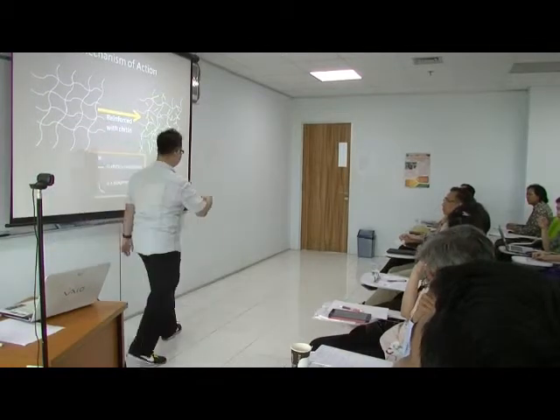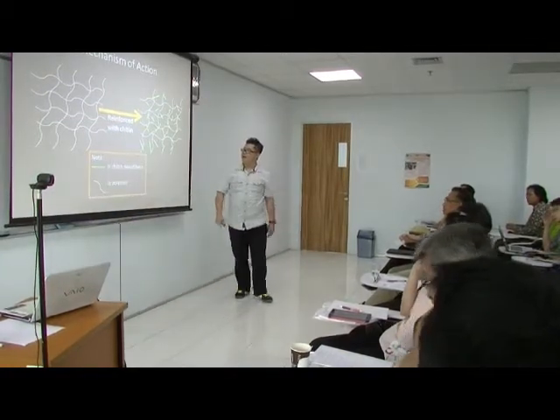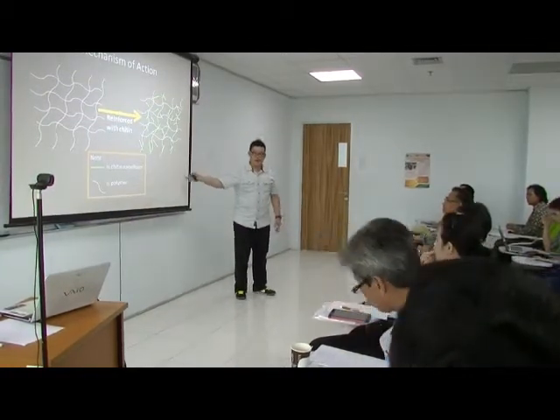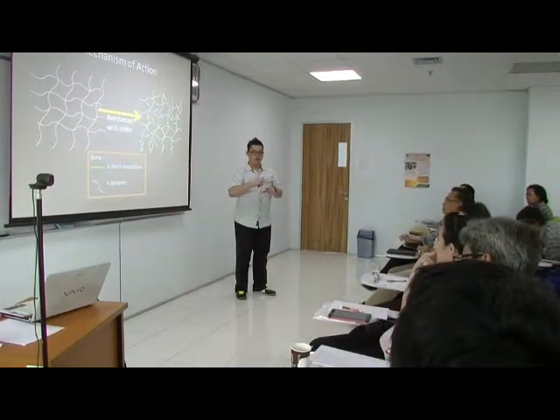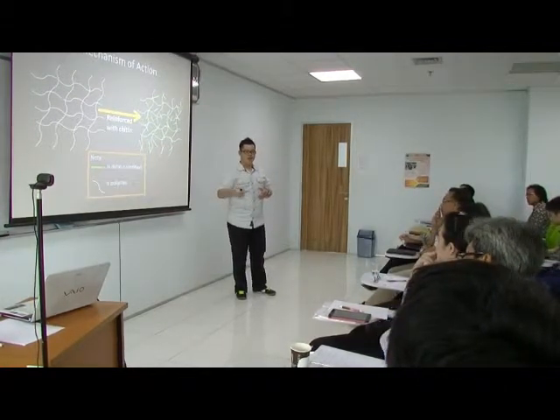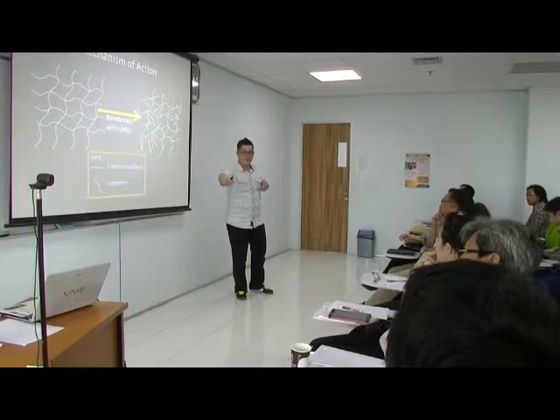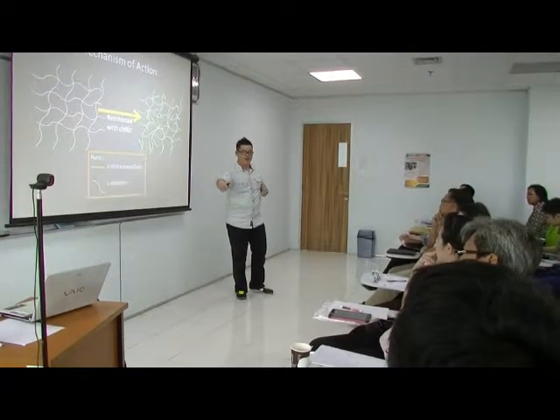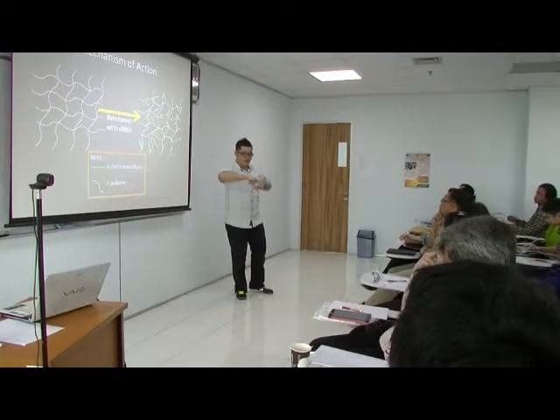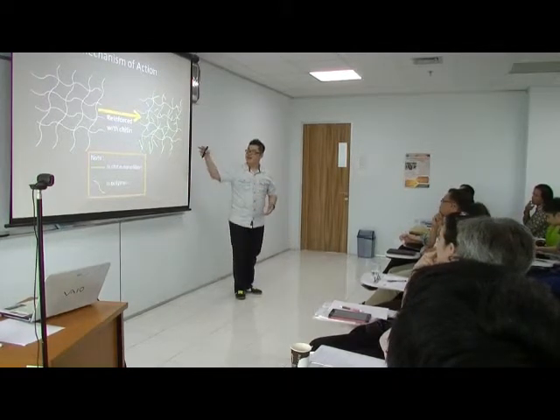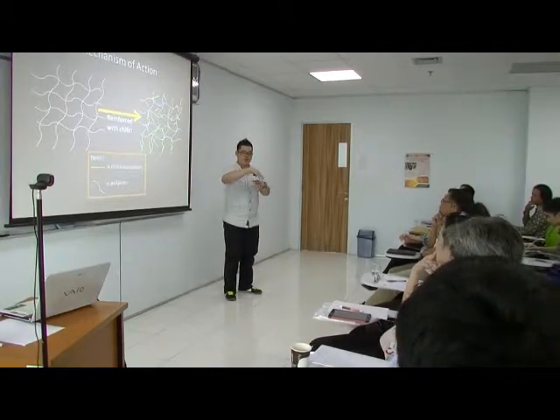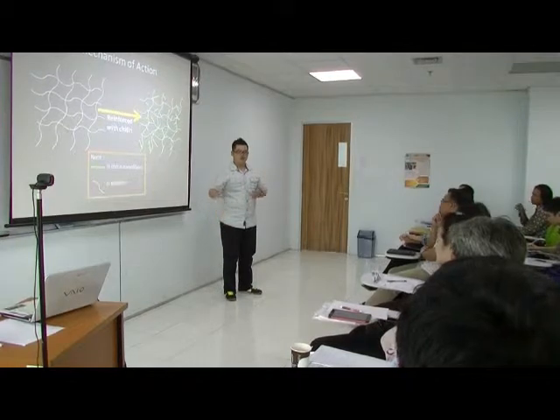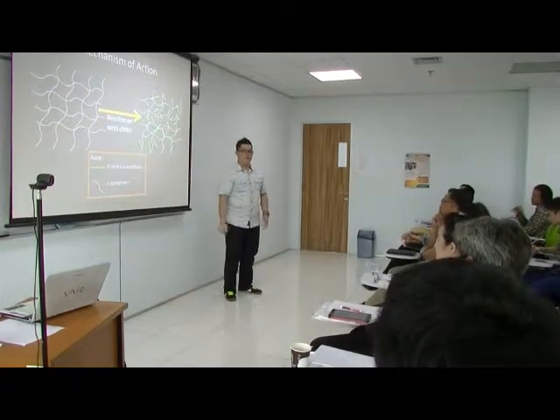So the chitin doesn't bind to the polymer, but it forms fibers, nanofibers, inside the polymer structure. If we say that when we pull a single paper, it will be much easier than if we pull a double paper or triple paper. It's like the chitin forming another structure inside the polymer. That's what makes the polymer stronger than before.